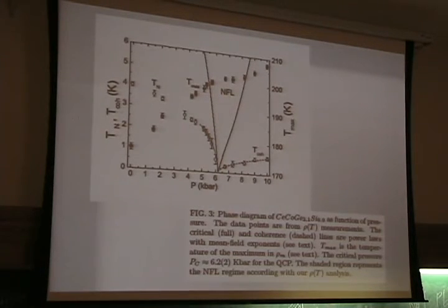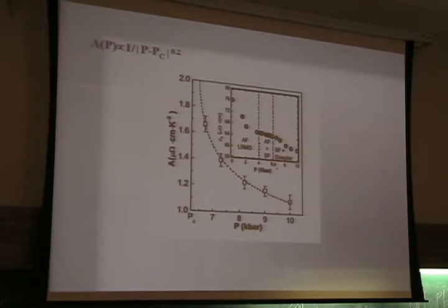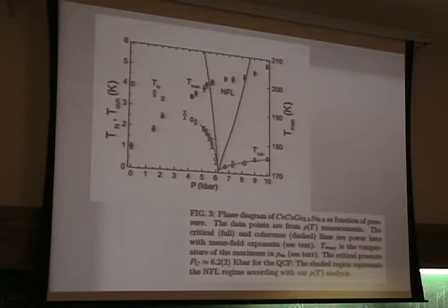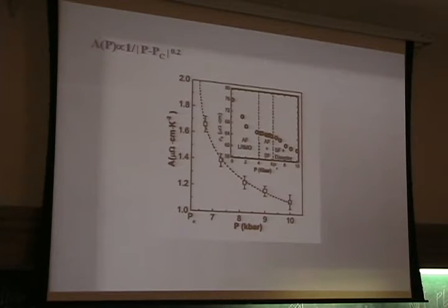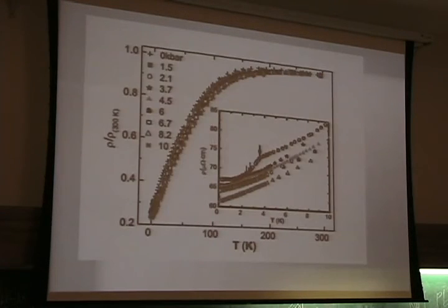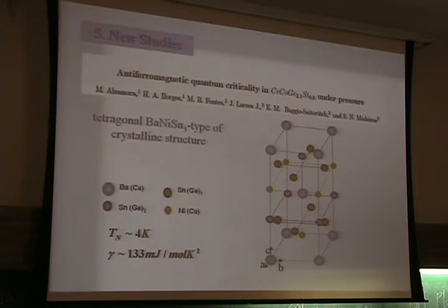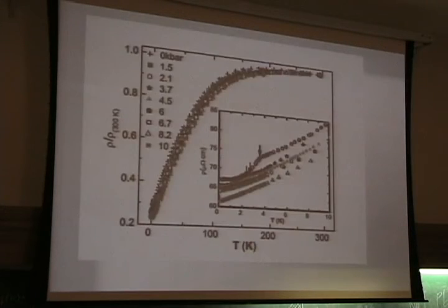But the T coherence, okay, and the A parameter that we took from this square behavior here, it's not diverging as fast as in the other two systems I showed you. So it may be because the disorder in this system is very high, since this kind of doping in general introduces a lot of disorder in the system.